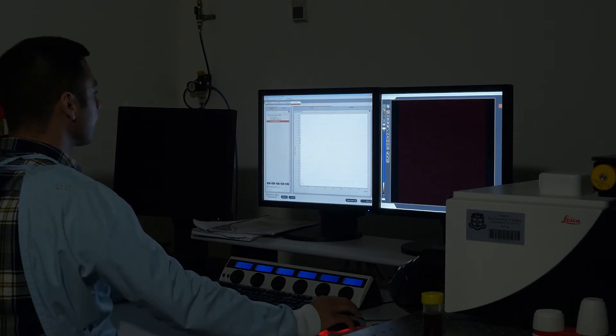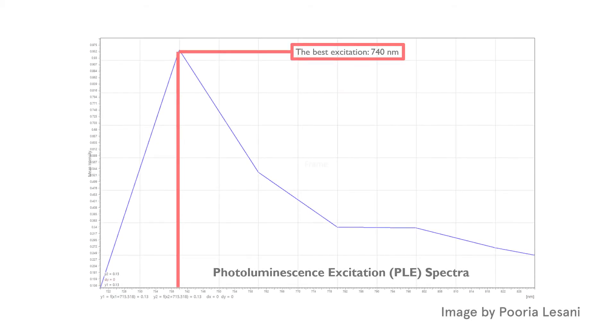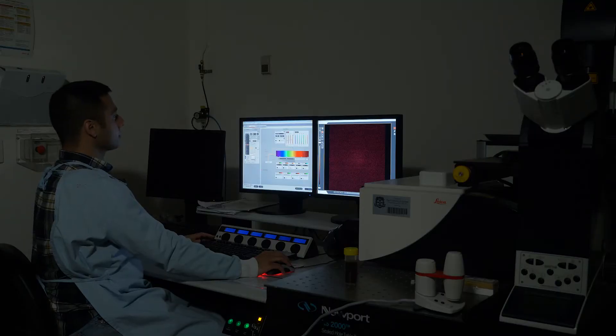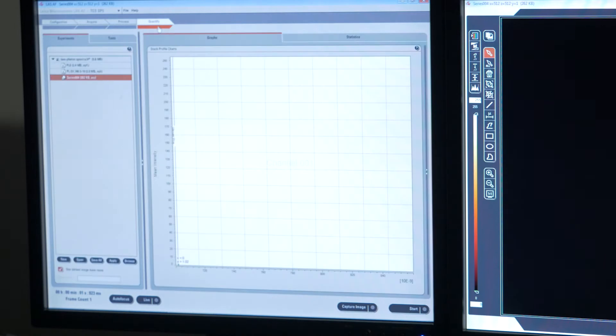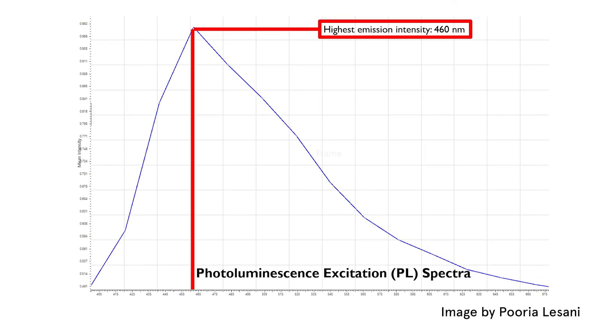As it shows here, the result is 740 nanometers. It means that at 740 nm we have the maximum absorption and the highest emission intensity. So we are exciting our probe with 740 nm, and here we collect the emission of the carbon quantum dots, which has the maximum emission peak at around 460 nm. Now I can show you how suitable the carbon quantum dots are for cell imaging.